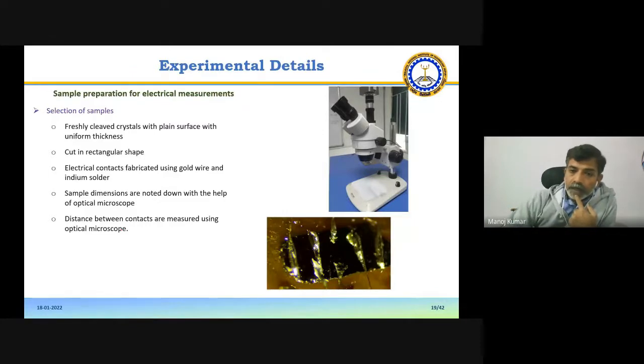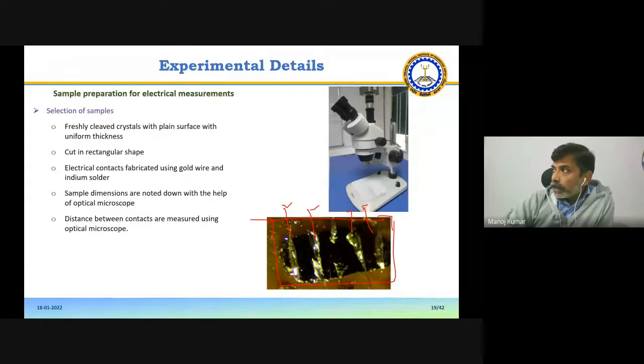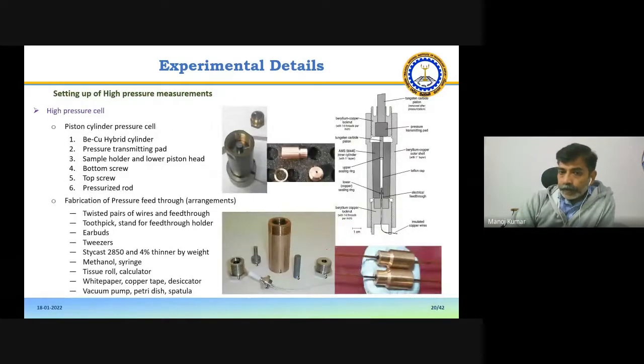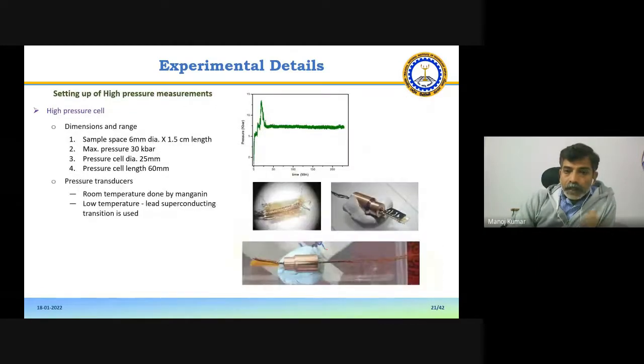Before measurement, we need to process the samples. As you can see, here is a picture of one piece of sample. For electrical conductivity, we use normal 4 probe measurements. These 4 probes, they can be used to measure the resistivity of the sample. And additional, these 2 probes, they are here to measure the Hall voltage of the sample. And we measure this simultaneously. Okay. And for the pressure measurement, we use a piston cylinder type pressure cell that can go up to 30 kilobar. And we can mount actually multiple samples at once in this pressure cell.